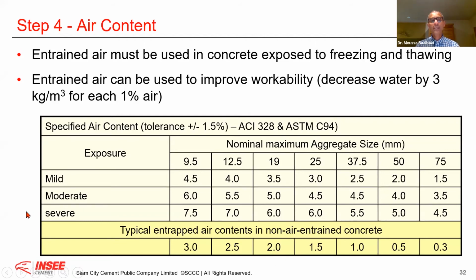But for example, in severe frost conditions, in Nordic countries, they can go up to 6% of air with this type of coarse aggregate maximum size. That is almost 4 times more air, but this is not entrapped air, this is entrained air. It's totally different. For this you use an admixture to entrain air.